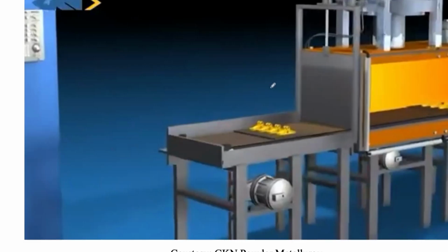So this particular feedstock, when it is being fed to the extruder head, goes through a nozzle. The head supplies the temperature sufficient enough to transform the polymer part, and then in layer by layer fashion, the part is being printed. And what about the metal powder? The metal powder is just sitting there as a filler somewhere in the system. Okay, so this is the first step.